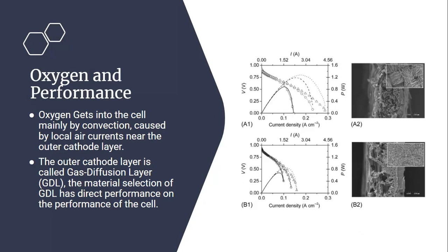As we see here in the graph, we have two materials, A and B. We found that A is a porous material which can let air pass through it, while B is less porous. So in material A, when the cathode or the anode are well aerated, they can let oxygen pass more easily, as convection is an important process in the electrolytic reaction. So A is more porous. We see in the graph that there is more current density, and therefore more voltage, while in B, it's less porous, so there is less voltage and less current density.